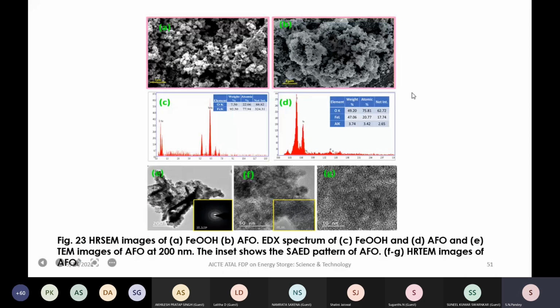One can see the HR SEM image. From here to here, it is quite different, and we observe that the surface has increased, as seen with the help of the SEM images. And then the C part, where the FeOOH and AFO have been compared, and one can see C and D.